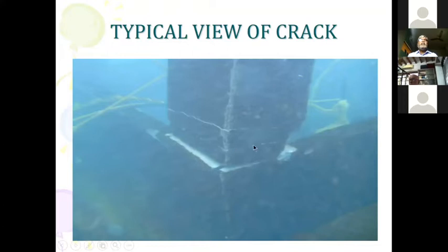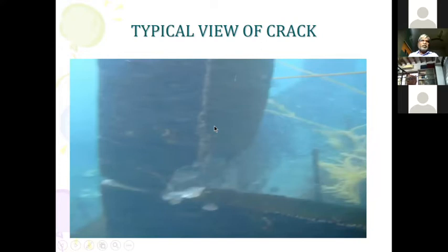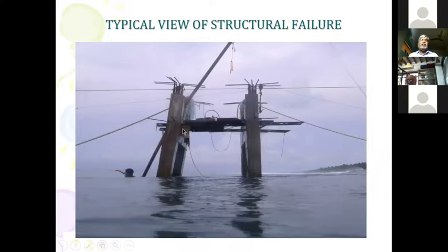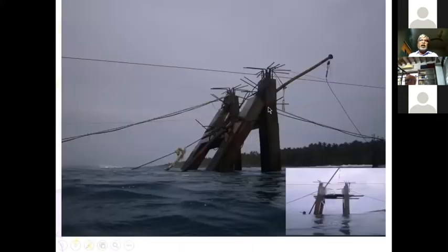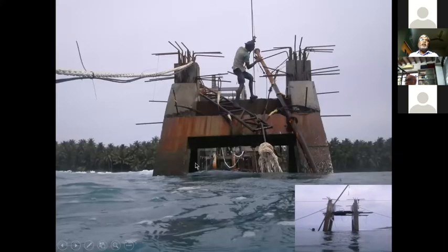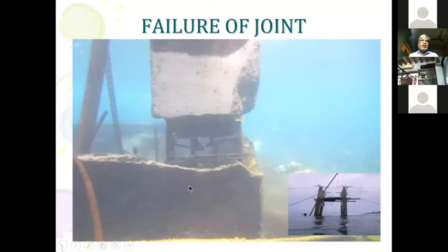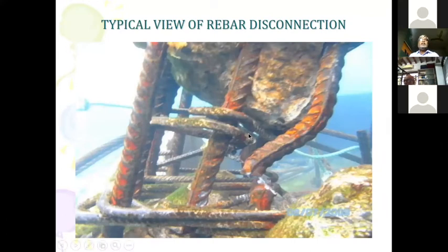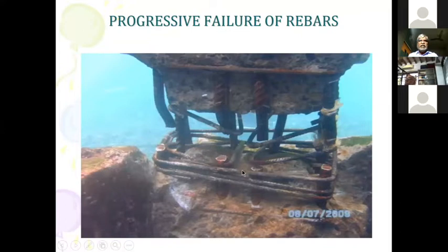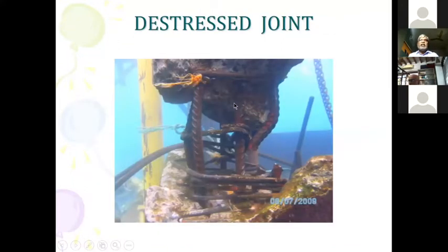But we went underneath. We found that there's a crack taking place in the 2 columns of your foundation, which started slightly as a crack and started leaning, and then the crack widened, and then concrete started falling, and it started leaning until at one point in time it came and touched the other 2 columns, where at the bottom you can find absolutely no concrete where the raft and the column join. And after these columns touched the other 2 columns, once the moment was over, shear came into effect. These 4 bars of 20 millimeter diameter got completely cut as if cut with a cutting machine or a hacksaw frame, and all these ties are not in position, and this is what happened.